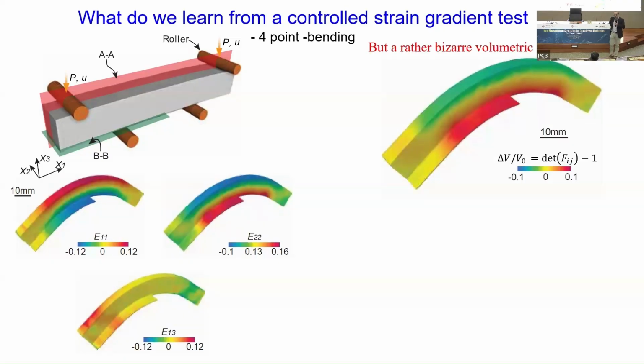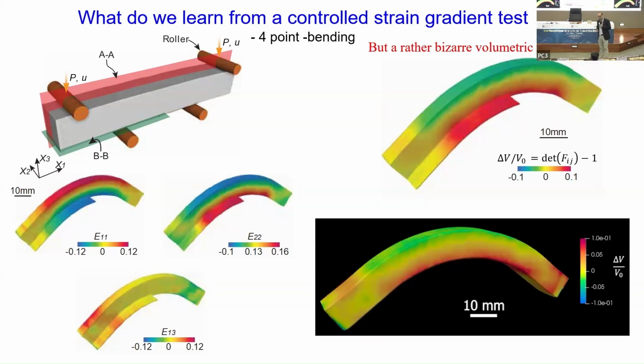But if you look at that volumetric strain again, where I'm now plotting determinant of F minus 1, you get really bizarre behavior. What you observe here is that on the compressive side, I'm seeing red. Basically, that means I've got a 10% volume increase here and approximately a 10% volume decrease on the tensile side. Now, this seems really bizarre, that I'm going to get a 10% volume increase on the compressive side. And this is not some surface artifact. In fact, this was an internal section that we were showing you here, because these were all from X-ray measurements. If you walk through the specimen, you get basically the same thing. It's pretty much all through the specimen.